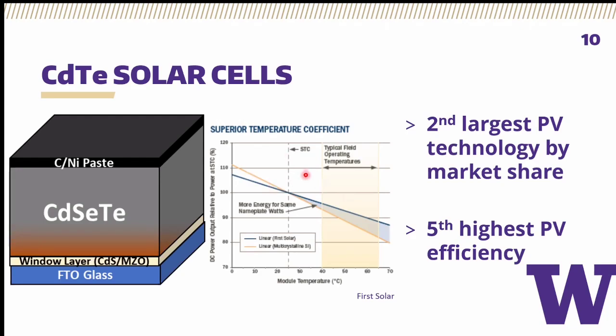CdTe is actually preferable to silicon solar cells in warm weather climates, such as in the American South, the global South, in North Africa, things like this, because they have much better efficiencies at higher temperatures relative to silicon, meaning that you can get cheaper electricity at these high temperatures with a CdTe device.